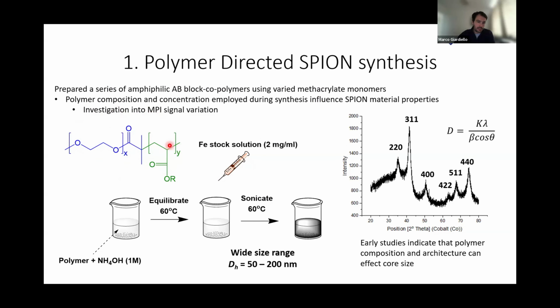And we've made a whole library. We've got tons of these polymers with various different groups. And we are looking at the impact of polymer composition on the overall structure of your particle. I refer to that large thing on the previous slide as the blueberry muffin, the blueberry being your iron oxides and the muffin being the polymer surrounding them. So we're looking to see what effect the polymers have on the muffin, the size distribution and its behavior, and also the impact that has on the growth of those particles, the blueberries, inside your blueberry muffin.